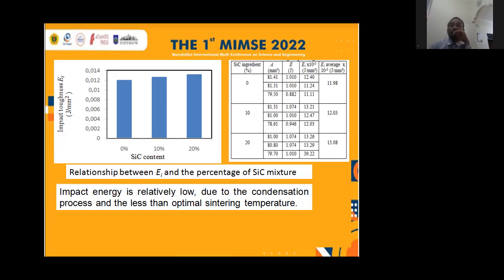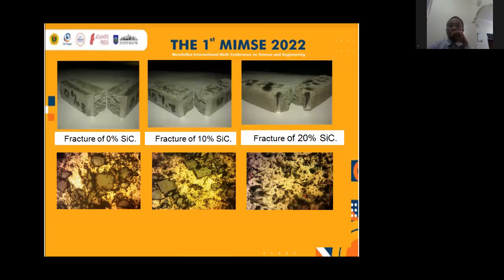The SiC ingredient, or percentage of SiC, affects the result of the impact toughness and absorbed energy. We can see here that the impact energy is relatively low due to the condensation process and the less than optimal sintering temperature. We can also see here the differences among three variations of SiC ingredients.